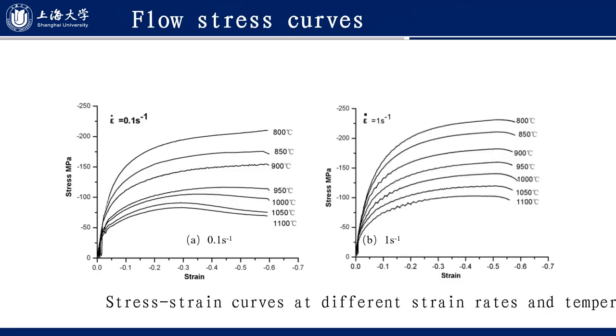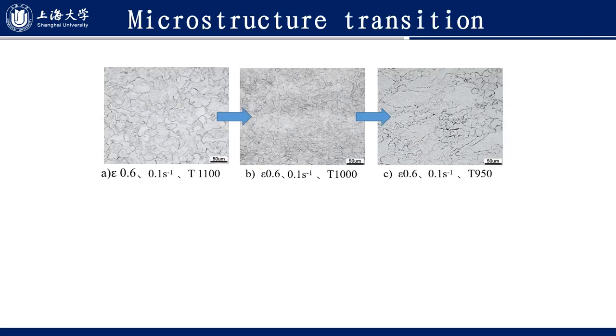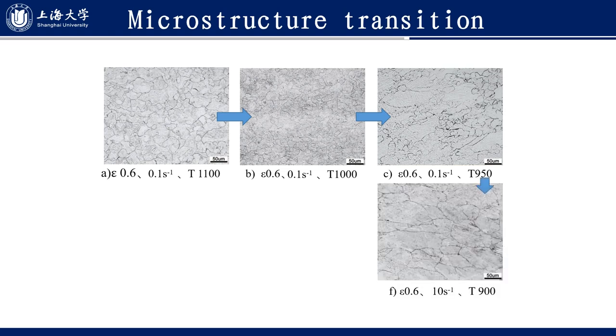This slide shows the flow stress curves of the steel with different strain rates deformed at different temperatures. The deformation temperature is between 800 and 1100 degrees C. Let's look at the microstructure transition of the steel during deformation. With temperature decreasing, the microstructure changes a lot.